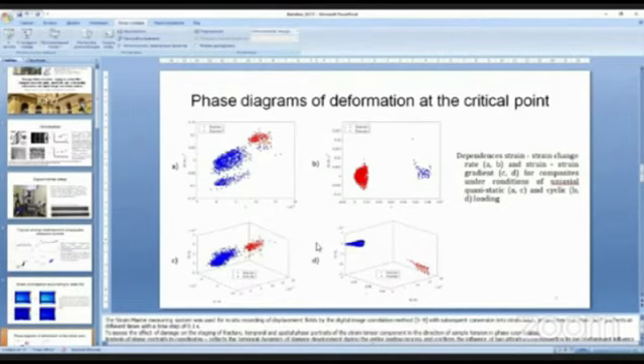And we can observe two clusters can be associated with two attractors corresponding to a singular solution with a stress intensity factor and non-singular solution associated with T stresses. At the same time for quasi-static loading, the division into such clusters is not so obvious. For fatigue loading they are far away from one another.